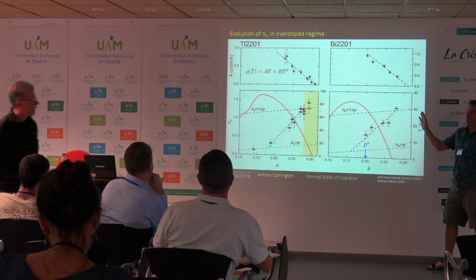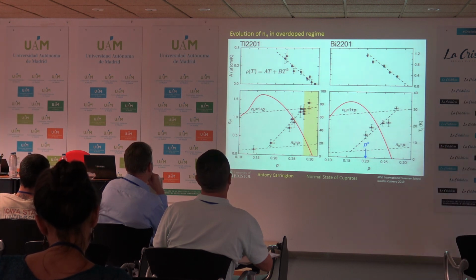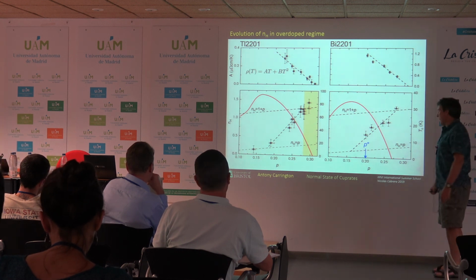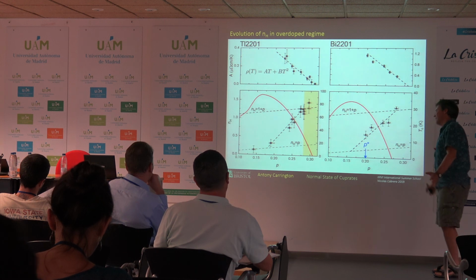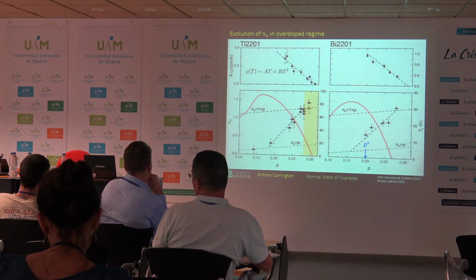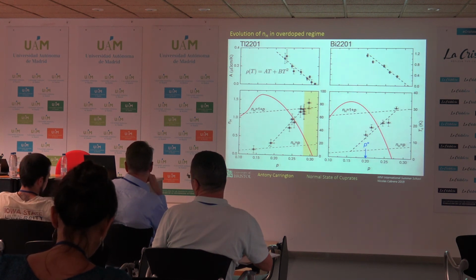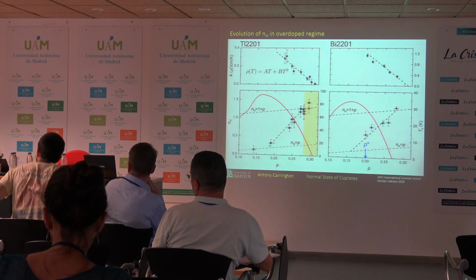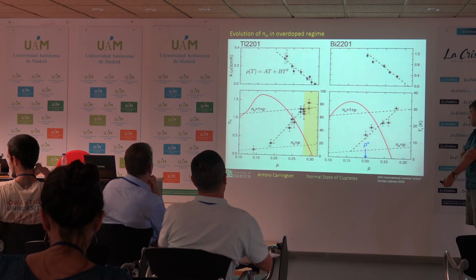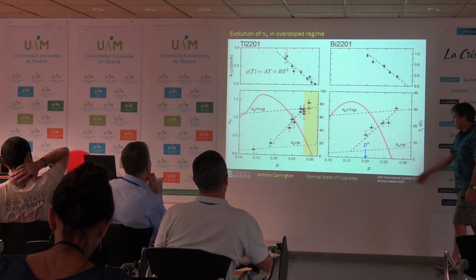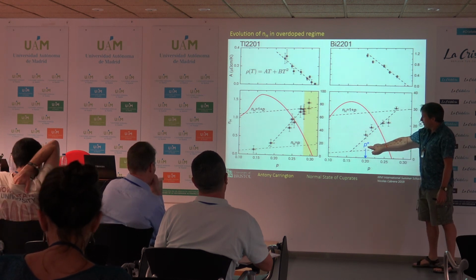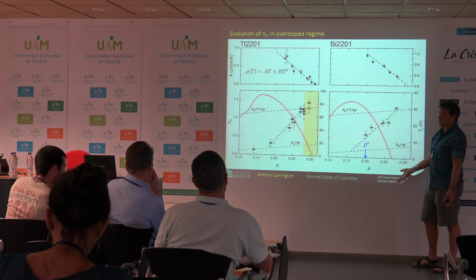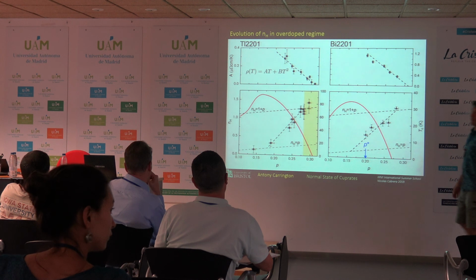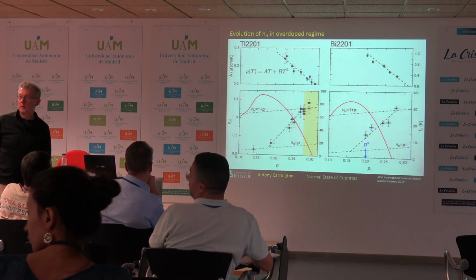I understand. But in principle, all manner of reconstructions are possible. So as a follow-up, where is the CDW regime in the bismuth-2201 plot? It's in the window where it's sloping up. It starts over on the left at low doping. It's decaying in its intensity as a function of increasing p, and you have lots of disorder, so you can't say it exists at one p and it disappears at another p. It's patchy, but it's gone by the time you get to 1 plus p. There are people that claim that there's also a patch over here. In bismuth-2201, you can quite clearly identify, from resistivity anyway, the pseudogap, at 0.19.